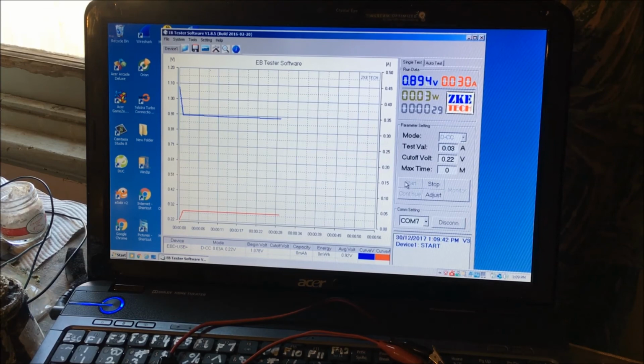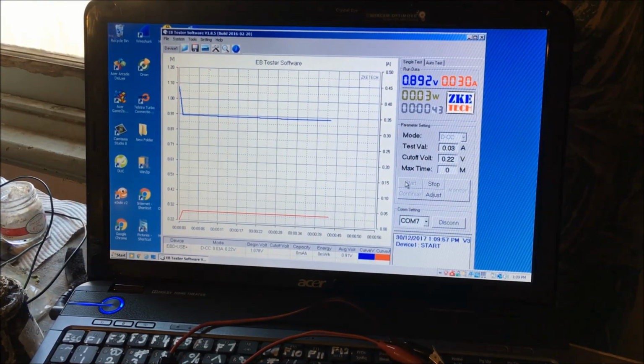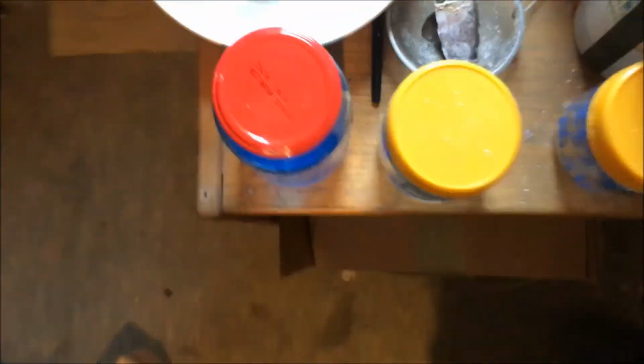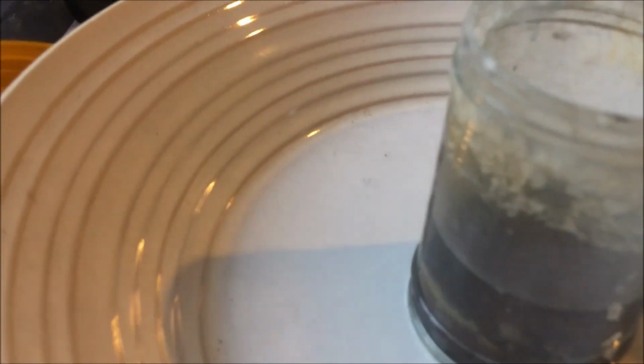So it does look like it's okay. The zinc carbon cell, negative cell, could be still okay, and it was this carbon electrode that's collapsed. A lot of copper is at the bottom of that container at the moment. And while we're waiting, I'll show you the tub that we did the galvanic cell test in with the copper sulfate and the zinc sulfate. Most of the copper's at the bottom with some zinc there as well, but this has been sitting around for a week and a half.